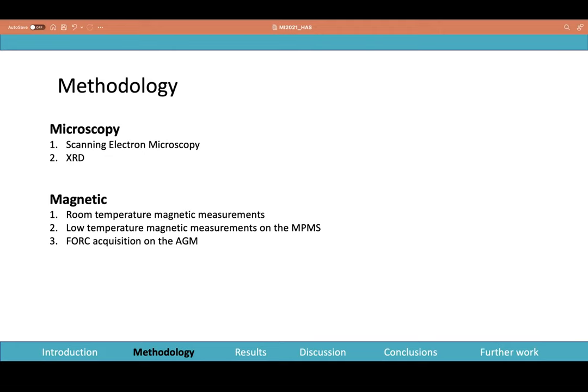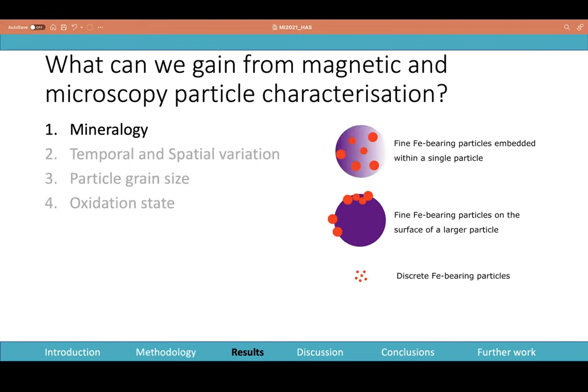Then our second set of measurements involved FORCs, which were done on the AGM at Cambridge. Then there was another set of low temperature magnetic measurements done on the MPMS. Basically, we had powdered leaf samples, we had dried them down, and we measured the low temperature IRM to look for SP contribution and any evidence of oxidation.